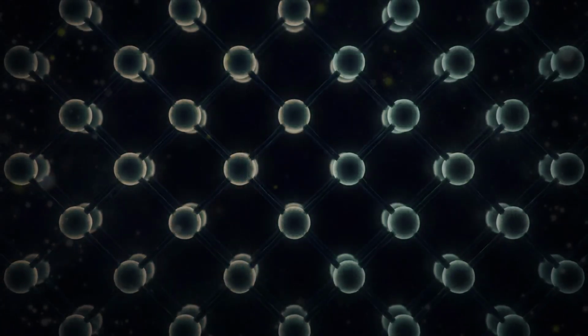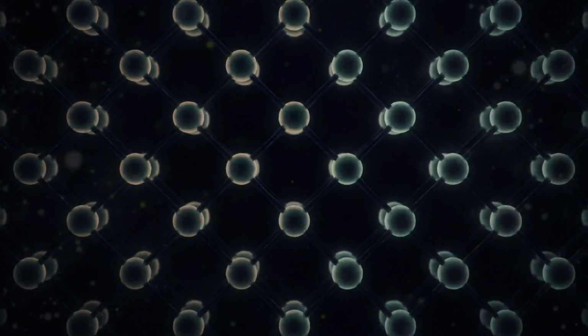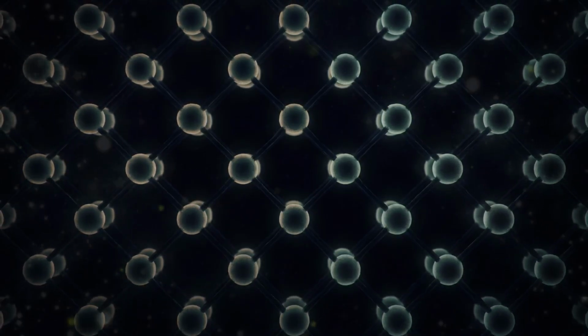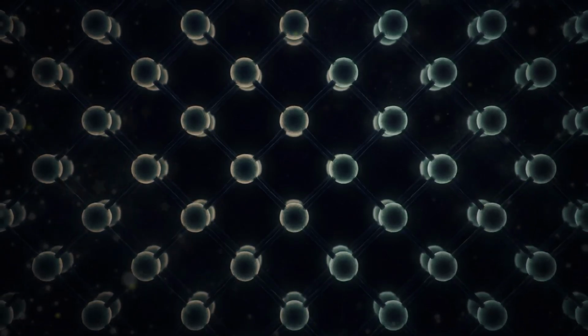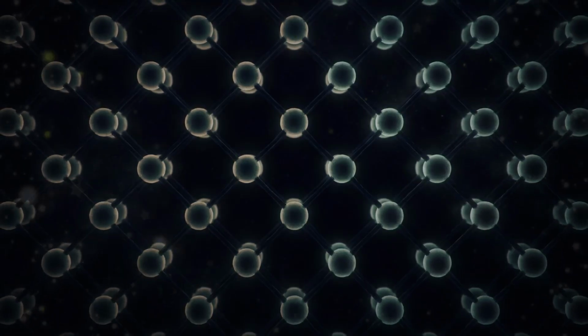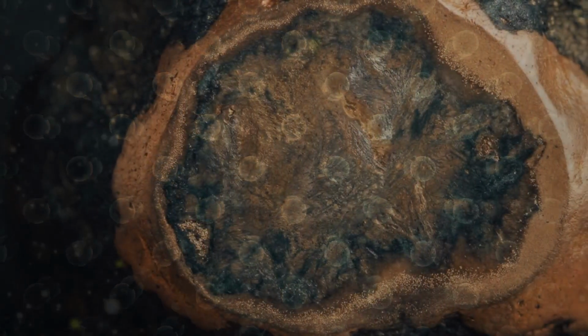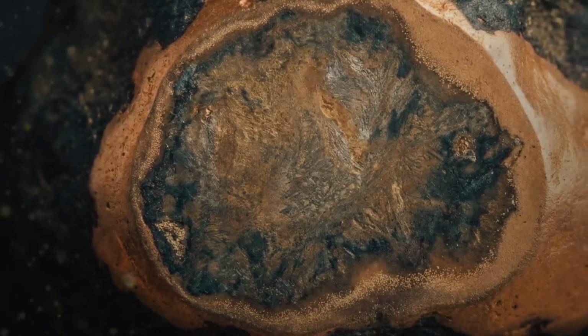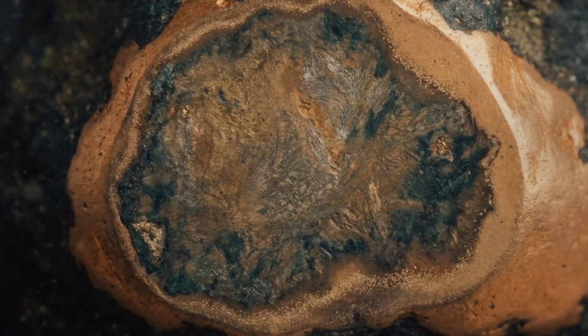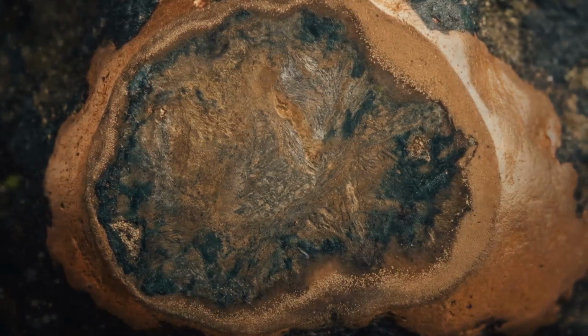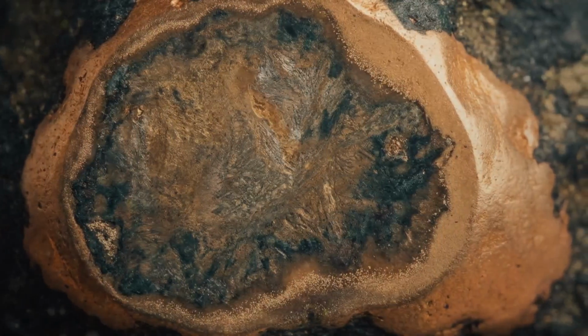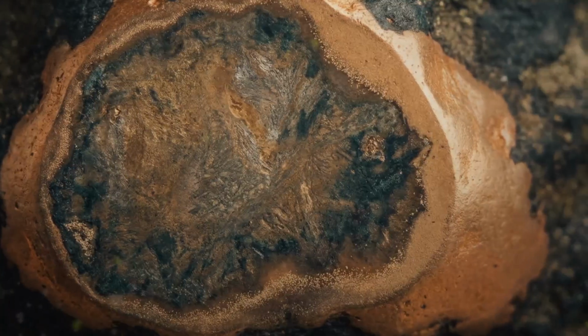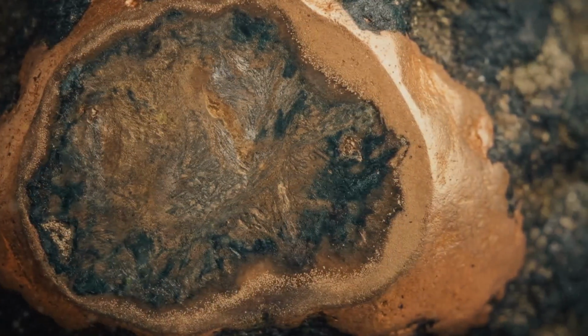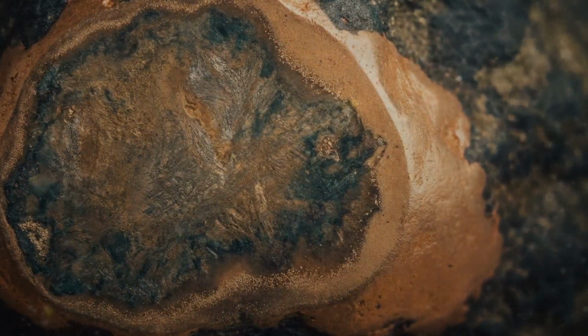Naturally occurring gold is rarely pure. It almost always contains some silver, the two elements forming a continuous solid solution series called electrum at higher silver contents. The silver content of natural gold varies from a few percent to over 50%, depending on the temperature and chemistry of the hydrothermal fluid from which it precipitated. Higher temperature hydrothermal gold tends to be richer in silver. Supergene gold, gold chemically purified near the surface by weathering processes that preferentially dissolve silver, tends to be purer. A supergene gold nugget may have a bright, high-purity outer zone enriched by selective silver dissolution, overlying an interior that still carries the original silver-bearing composition.